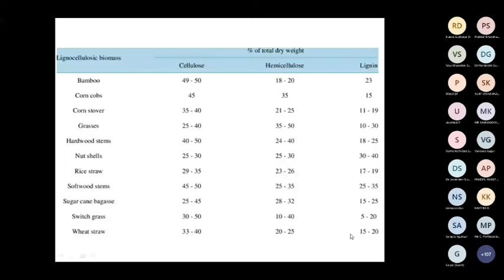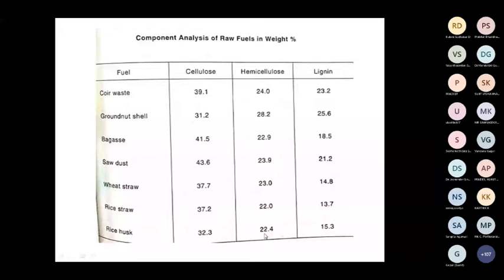Grasses under 35 to 50, 10 to 40. Whatever biomass fuels were studied, cellulose varies from, say, 39 to 41. Hemicellulose is 24%, with close variation, 22 to 24%, except groundnut shell alone is having 28%. So hemicellulose in groundnut shell alone is highest among the biomass fuels studied.